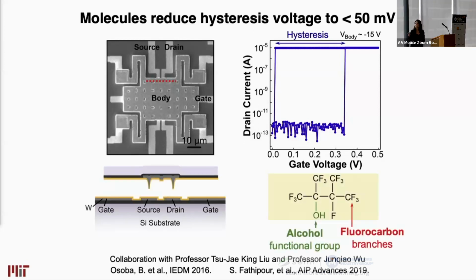So now if we functionalize the contacts in this device with this molecule, with a fluorocarbon and alcohol end group, allowing its assembly onto the tungsten contacts of this device, we're able to operate the device at an extremely reduced hysteresis voltage, less than 50 millivolts in this case, providing an opportunity to have these devices operate at lower energy. This work is done in collaboration with Professor Tsu-Jae King Liu and Junqiao Wu at UC Berkeley.